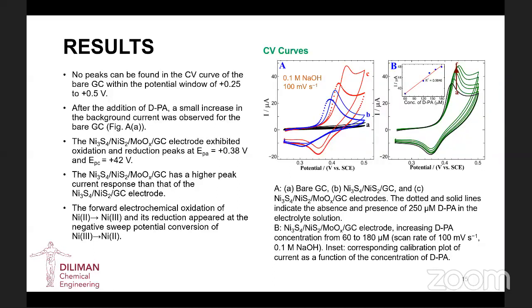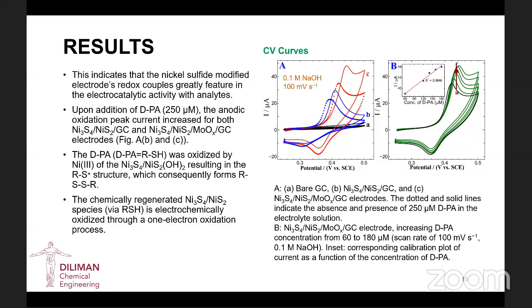and in its reduction appeared at the negative sweep potential, the conversion of nickel 3+ to nickel 2+. So this indicates that the nickel sulfide modified electrodes' redox couples greatly feature in the electrocatalytic activity with the analyte, or in this case DPA. And then upon addition of the DPA, the anodic oxidation peak current increased for both electrodes.